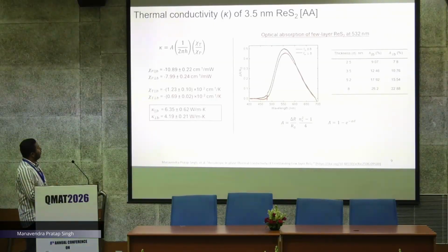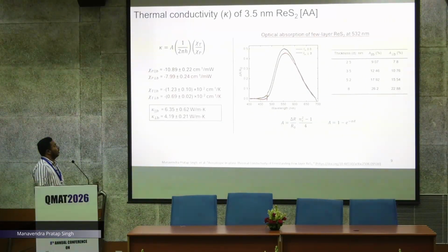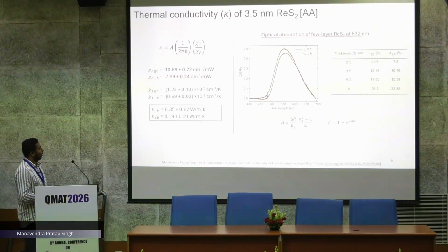So using that formula we have to calculate the thermal conductivity, but in this formula there is the actual absorption of the material. For that we have performed a white light reflection measurement to calculate the actual absorption of the material, and for that we have also taken care of the polarization of the white light and calculated our absorption parallel to the b axis and perpendicular to the b axis.